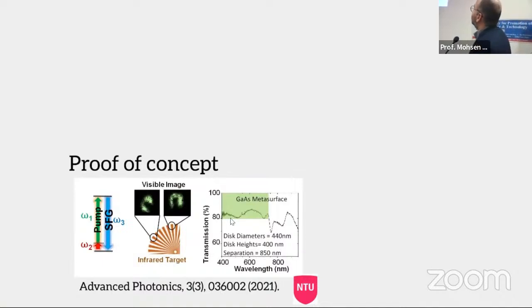frequency of the light. And here is the very first prototype we showed. This target was illuminated at around 1500 nanometers, and these images are taken at 500 nanometers. You see the greenish color. This is taken by a visible camera, a camera which doesn't detect the near infrared, but the input was near-infrared light. Of course, efficiency is still low. We cannot see it with our eye, but the visible camera is the equivalent of our eye, but stronger and more sensitive. Here I want to draw your attention to this green box, which shows that our metasurface in the visible range, which is 400 to 700 nanometers, is more than 80% transparent. So it means that you can see this and also the near-infrared light at the same time.